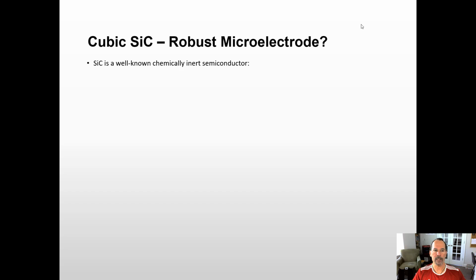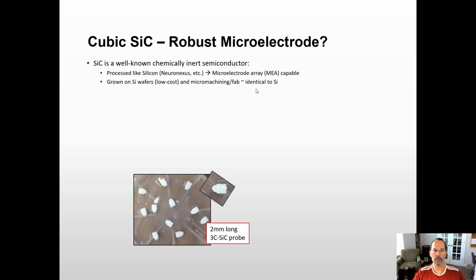So why is it that we believe that this would make a great robust microelectrode? Well, again, it's an inert semiconductor, basically a ceramic. We can process it just as NeuroNexus does for their MEAs and implants. We can grow it on silicon wafers, so we can micromachine the same way we do silicon. And here's an example. This is a relatively old picture of some 2 millimeter long blank probes we've done up to 1 centimeter without any problem.